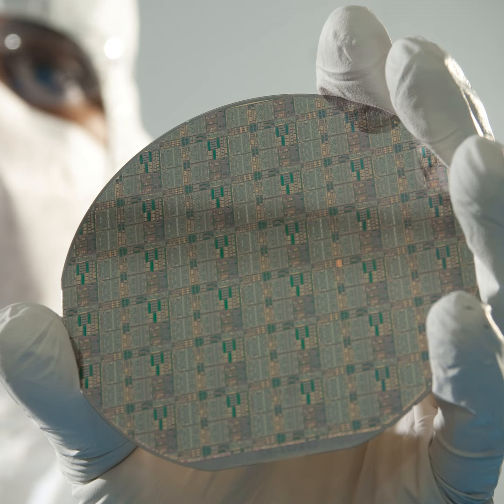Now, intrinsic to the device, there are other tricks we're doing to reduce the thermal resistance. One of those is addressing the GaN material itself. When we grow GaN, it typically has a buffer in the material that allows the GaN to be matched to its host substrate. We're looking at techniques to thin that buffer. The thinner it is, the less resistive it is. And then there are other materials such as aluminum nitride, which offer higher thermal conductivity, which can replace a good portion of that GaN buffer. So between the intrinsic material selection and the extrinsic diamond, these are some of the key levers that will get us to that 16x performance.